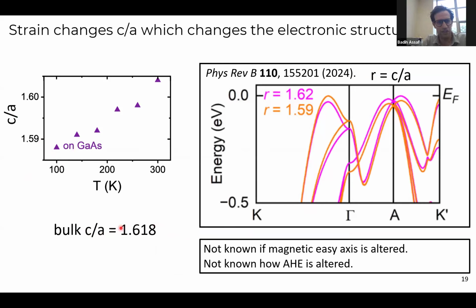Now, there are band structure calculations that have computed how this changing C over A ratio changes the electronic structure. And what these calculations have shown is that by reducing the C over A ratio, the valence band edge moves from being at the A point of the Brillouin zone to somewhere close to the gamma point of the Brillouin zone. It's not known, however, if the magnetic easy axis is altered, or if the anomalous Hall conductivity computed from Berry curvature is altered in any way. These are still open questions.